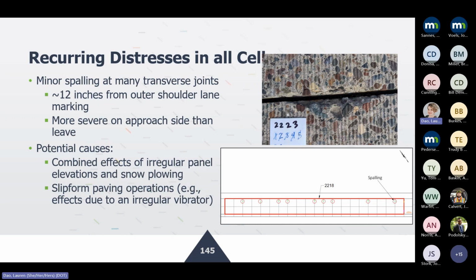We thought that, but we did put a straight edge and did not see anything out of whack there. It seemed to be okay. And then maybe snow plowing issues contributed to it. We also hypothesized that it could have been due to an irregular vibrator at the paver, but we don't know what the exact reason is. We did see a lot of low severity spalling through the entire length of almost every single slab there.